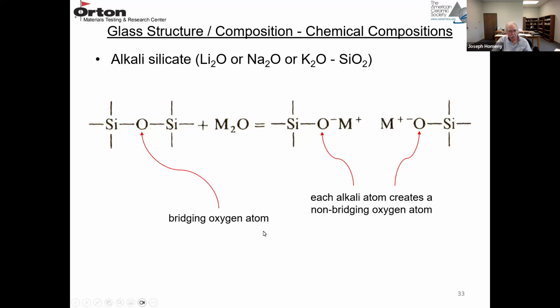So here's what happens when you add lithium, sodium, or potassium to an SiO2 glass. Here's your basic Si-O-Si bond. You have a bridging oxygen between two Si atoms, and you add M2O, which could be Li2O, Na2O, or K2O. And now you break that oxygen bond, and you have a Si-O-M and another Si-O-M. So this is a negative oxygen. The charge is balanced by one of these +1 cations, and another negative oxygen bonded by a plus cation. So each alkali atom creates a non-bridging oxygen. So one alkali oxide actually creates two non-bridging oxygens because there are two +1 cations.